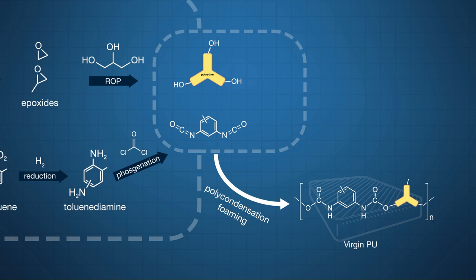In the presence of water, isocyanates are hydrolyzed to amines, which can further react to form urea groups. The hydrolysis also results in the formation of carbon dioxide, which causes the foaming.